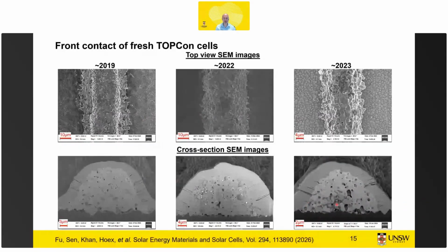So of course, soldering flux etches all oxides. So if the soldering flux can reach the interface, also all the oxides are gone. So that was quite a big development. So we see that after the introduction of laser-assisted firing, there's still some sensitivity, but it's less, and we will report more on that in coming months. So laser-assisted firing has made life a lot better, but it's not completely solved yet.